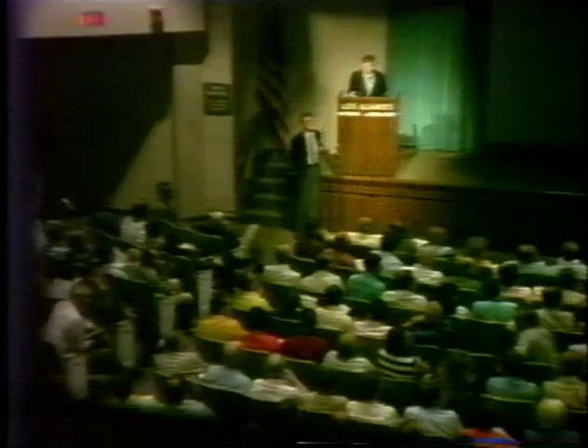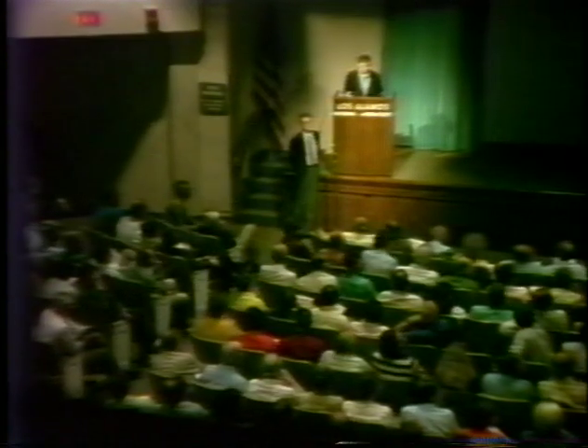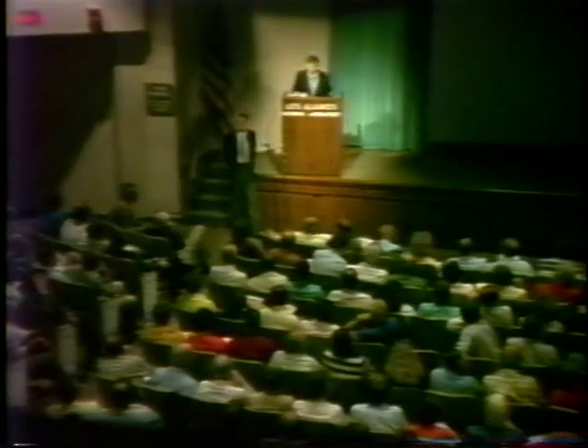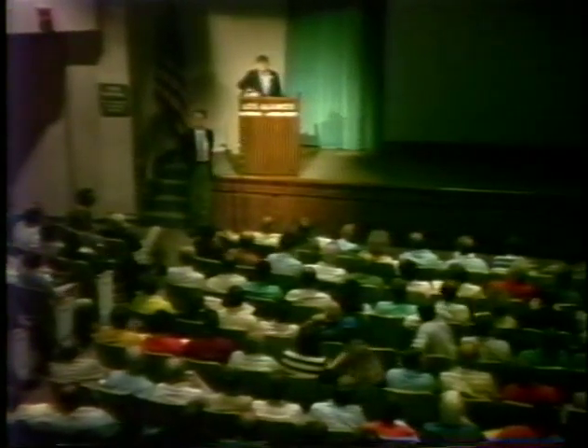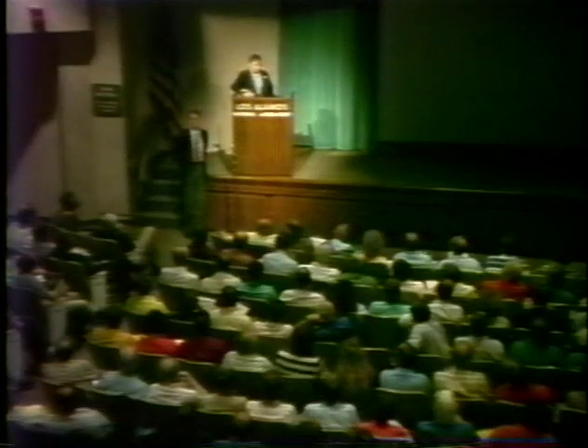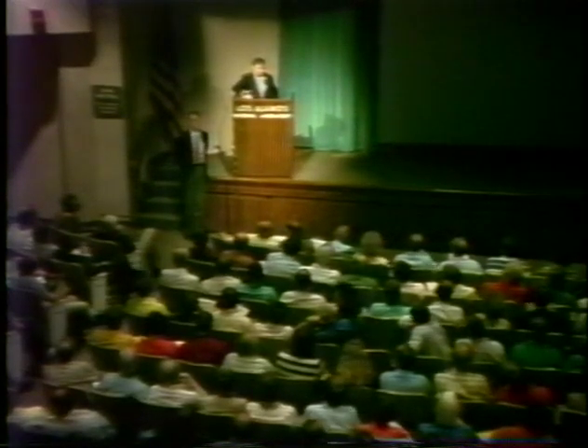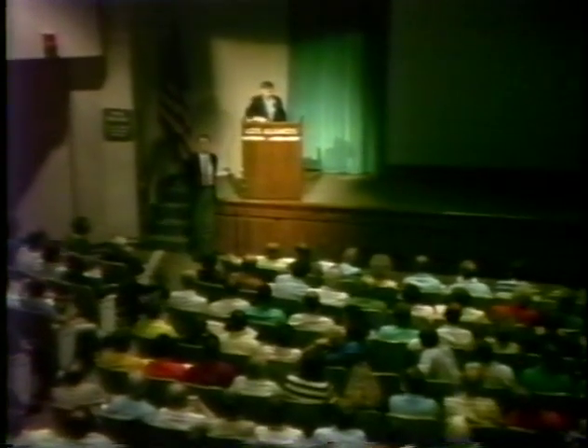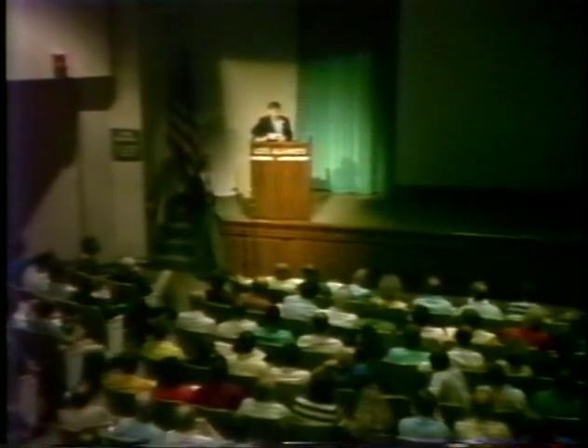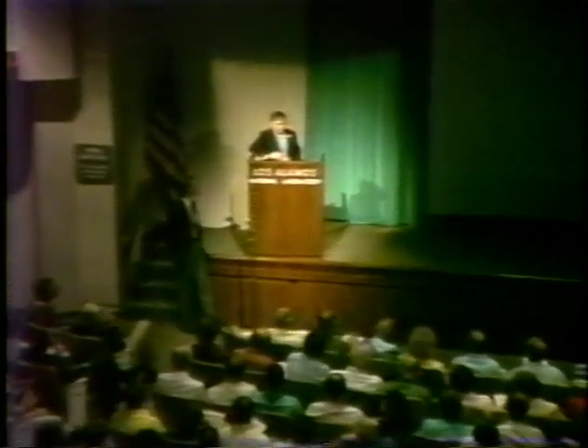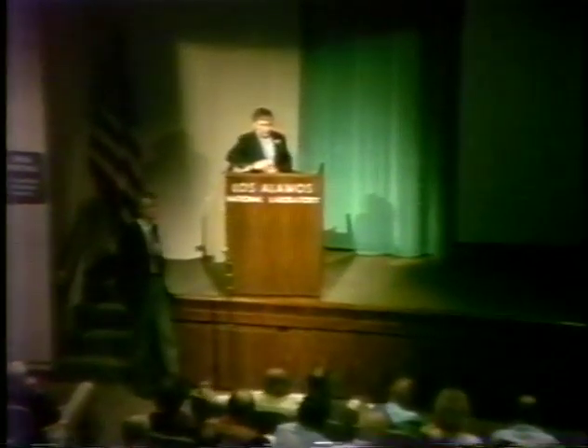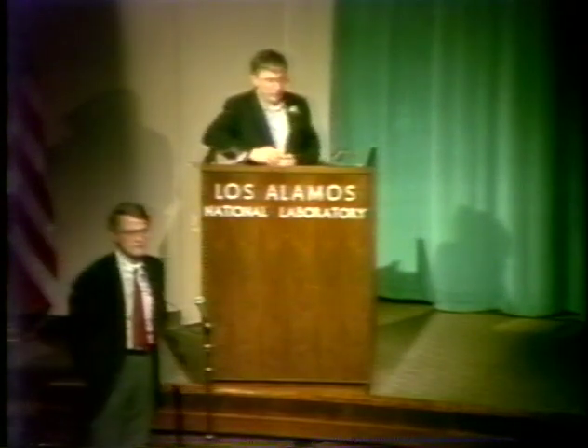Have you examined your palladium electrodes after the fact to see if there is any metallurgical change? We always believe the state of beta palladium hydride is extremely hard, a very hard substance compared to the soft raw palladium. But in these cases, when we finish with a rod like a 4 millimeter rod, the additional intercalation of lithium into the lattice makes it extremely hard, and it will totally destroy a brand new hacksaw blade if you try to cut it. We had to use about 2 blades and take about 15 minutes to cut a 4 millimeter rod. So it's an extremely hard substance, and so there definitely are surface metallurgical changes, at least with lithium present.